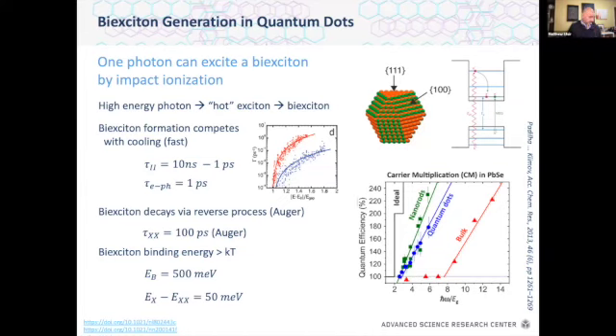So these are just approximate numbers, but just to give you an idea of the orders of magnitude, that's about 100-ish picoseconds. Okay, nevertheless, people have demonstrated using photocurrent and other types of measurements that Biexcitons can be harvested, that you can actually use this carrier multiplication process and get extra work out of the photons you put in. And you can demonstrate that despite some, again, reasonable binding energies for both the exciton itself and the Biexciton. The exciton binding energy on the order of ½ a volt and the Biexciton binding energy on the order of 50-ish millivolts. So binding energy is greater than kT, yet still we can harvest them and use them without too much trouble.